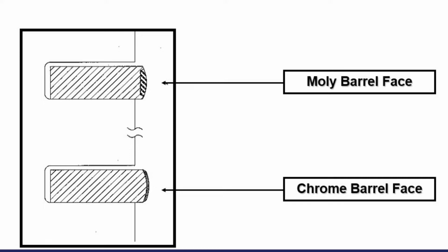And these pictures here, the top one's a moly one, and you do a lot of those still here at this plant. And as many of you know, to do the moly coating on the ring, you actually have to cut a groove into the face of the ring, a channel to spray that moly into. And you can actually see the little artist rendition there. On either side of the moly is ring material protecting that moly. So by laying it in there with protective edges of ring material, parent material, we protect that moly and keep it from fracturing and breaking out.